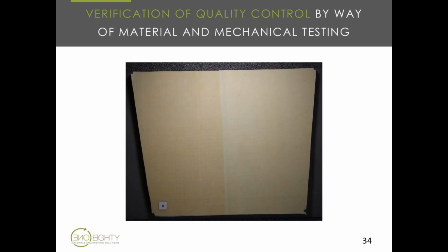And you can see very clearly here that's supposed to be the exact same color, but the milkiness was their indication that something had gone wrong during the curing process. So it was a visual cue that alerted them to this error, but it was the tensile testing that confirmed it and verified it for them.